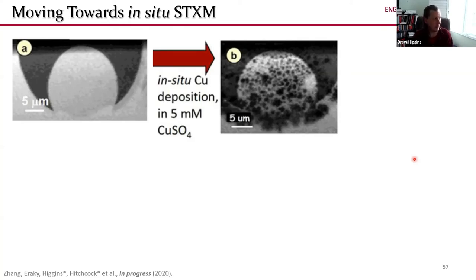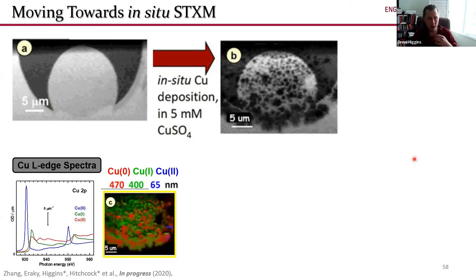So Chunyang electro-deposited copper onto these electrodes and then did some characterization, essentially took STXM spectroscopic measurements to figure out what types of copper were present in these materials. And what he found is that when you start flowing an electrolyte into the system, you have a bunch of metallic copper, copper 1+ oxide, and copper 2+ oxide present.